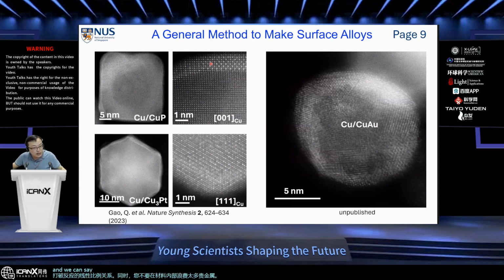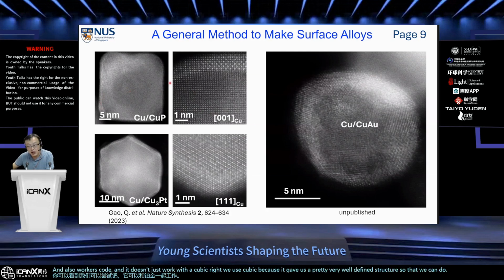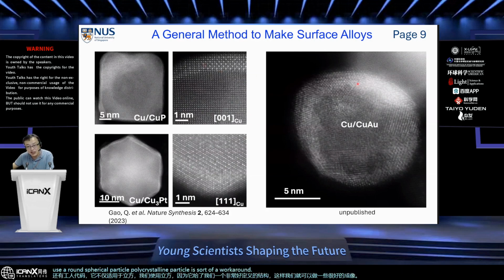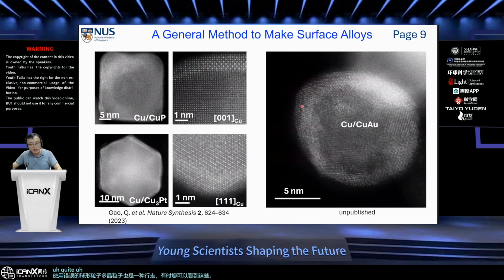And sorry, this word should be palladium. And you can see that we can try with palladium, it works with platinum, and also works with gold. And it doesn't just work with cubic, right? We use cubic because it gave us a very well-defined structure so that we can do some nice imaging. But if you just use a round spherical particle, polycrystalline particle, it will work as well. Sometimes you can see this intermetallic phase quite obviously. So this is very nice.